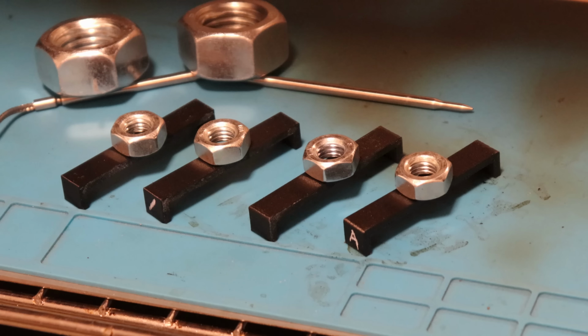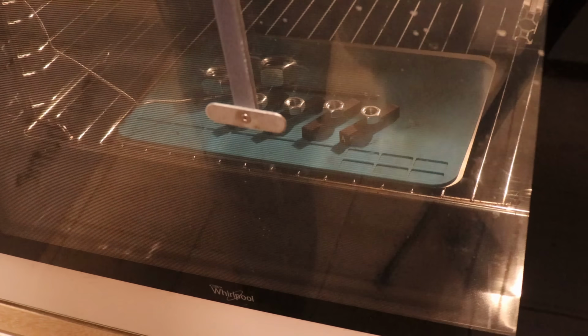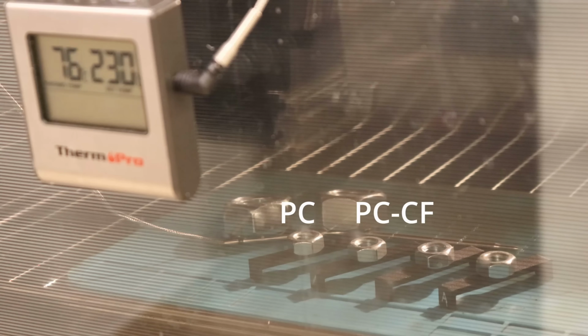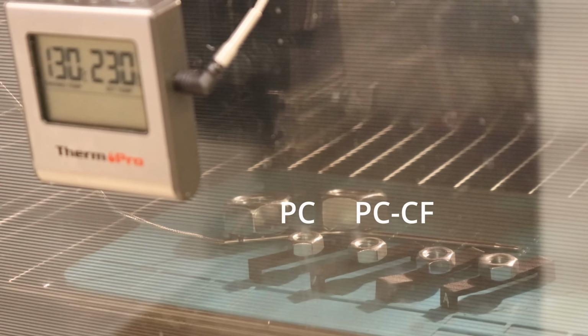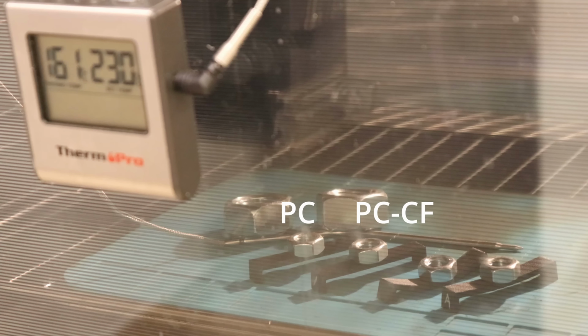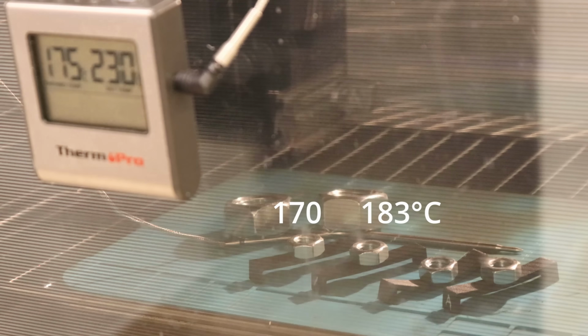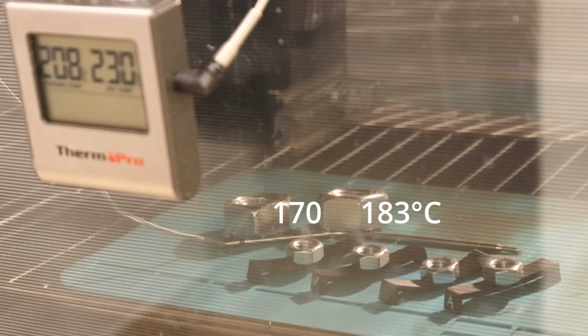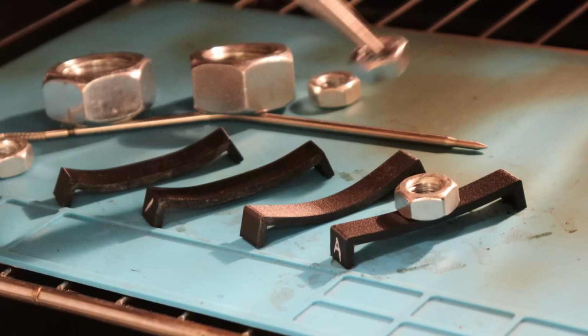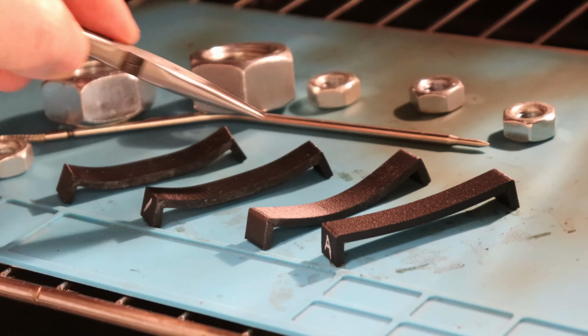Temperature test in the oven, and these are 2 filaments from this video. This is speed up time-lapse video. At the beginning nothing happened, and the first deformation I noticed on polycarbonate at 170 degrees Celsius, and very quickly after it, on 183 approximately, the carbon fiber version started with the deformation. The experiment I stopped on 220 degrees Celsius and I checked how flexible they are, and in both cases they are quite soft now.